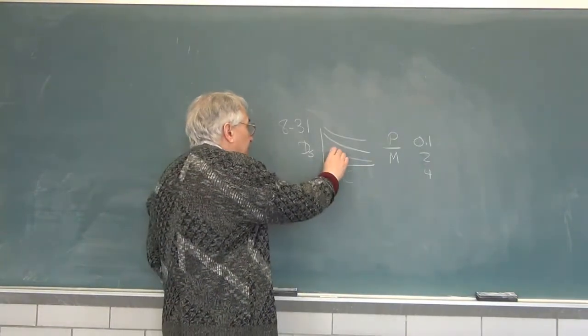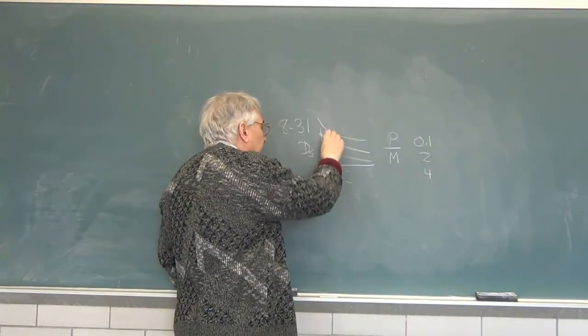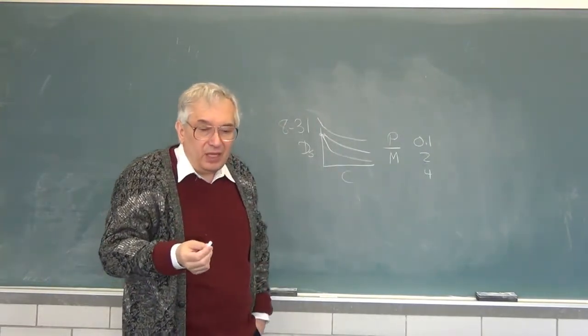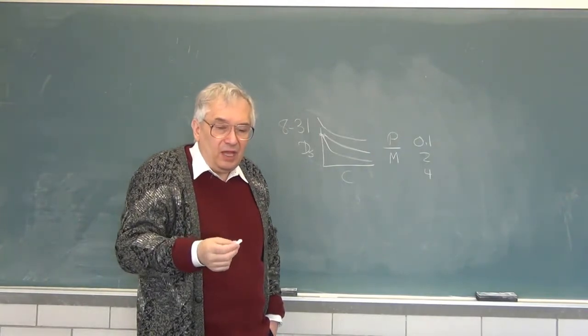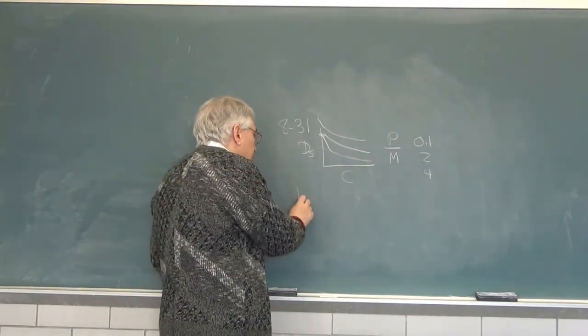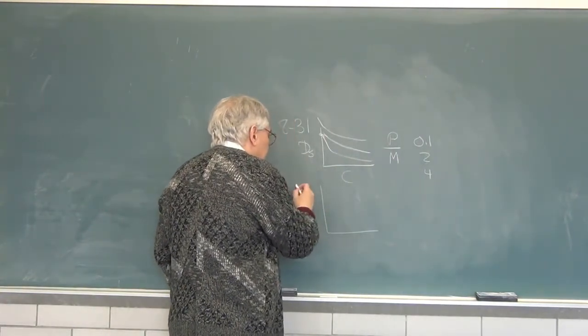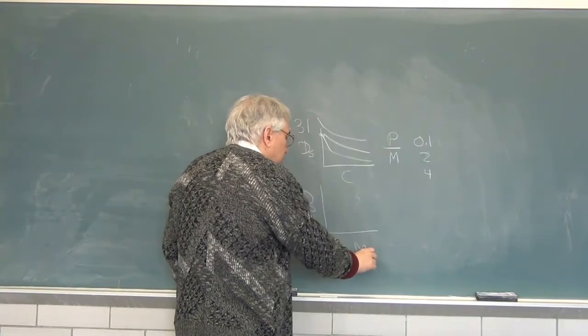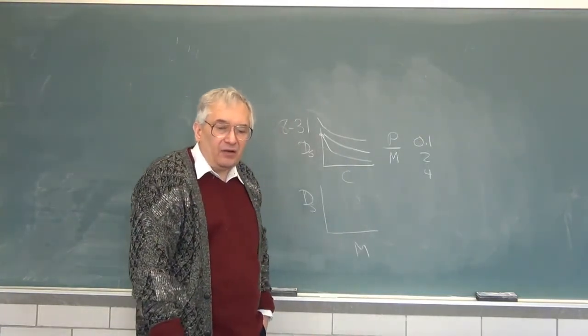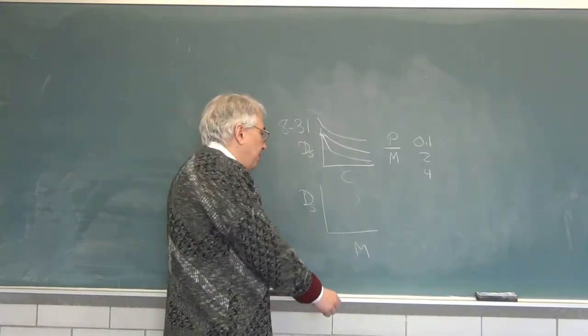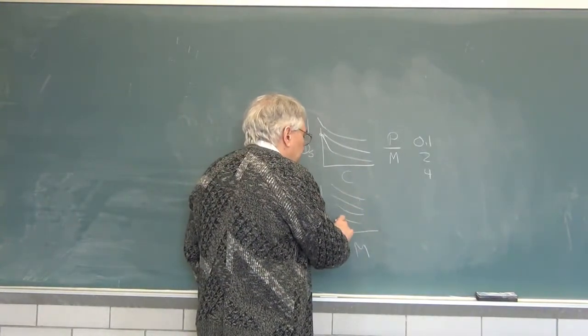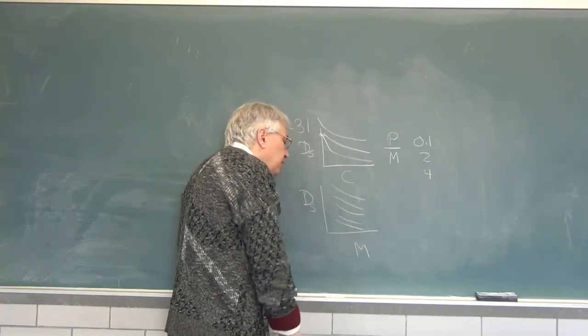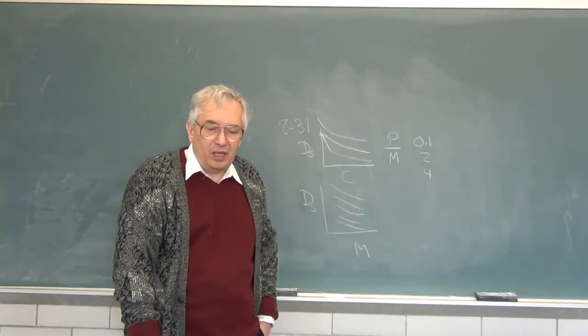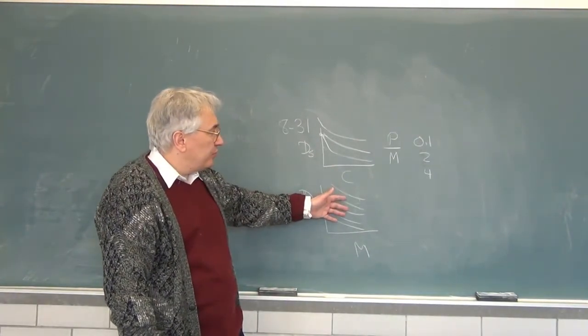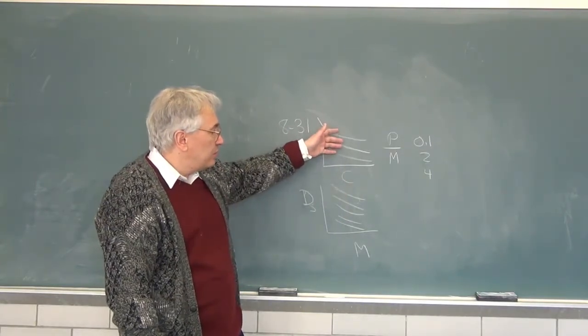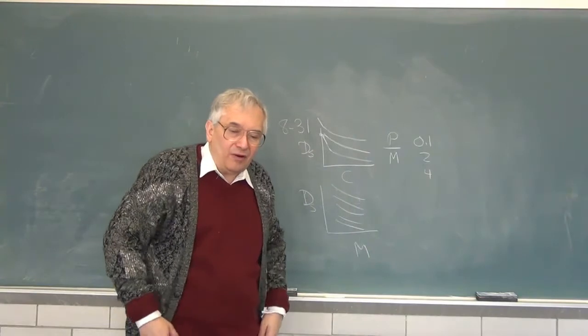And because of the way things are arranged, these two curves have to come together at infinite dilution. And gee, they're data, and there are smooth lines. And they also said, we will look at various probes. We'll look at DS again, and its various probes as a function of matrix molecular weight. And there are a lot of probes, and not that many matrices, but you see another series, family of lines, which mostly but not completely go through all of the measurements. The fit agreement of these curves with the measurements is not nearly as good as the agreement of these curves.